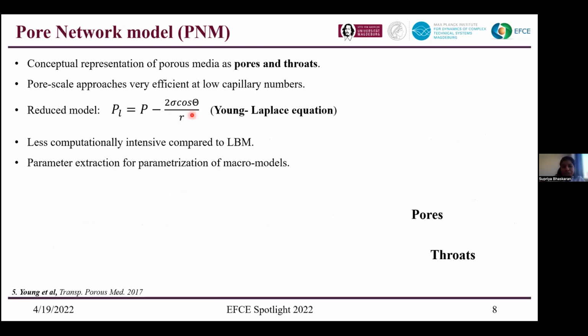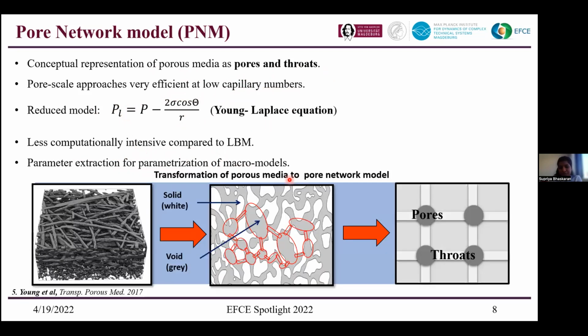And then we move to the pore network model. So here we have the pore network model, in which we represent the porous media as pores and throats. And it's a pore scale approach, which is very efficient at lower capillary numbers. And this model deals with the Young-Laplace equation, where we calculate the liquid pressures. And this is less computationally intensive than the Lattice-Boltzmann model. And also we can extract the parameters to our macro model. So now I would explain how we extract these pores and throats.